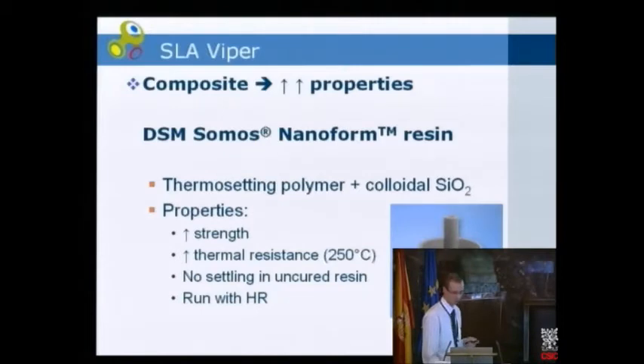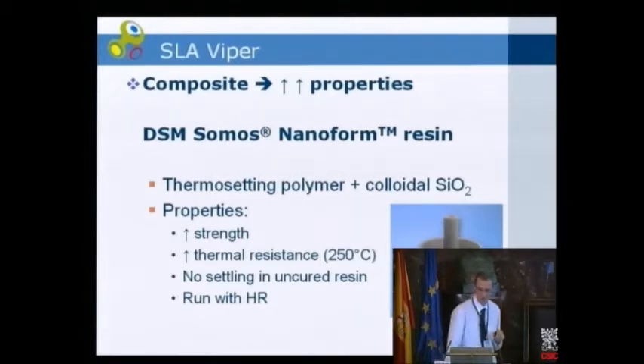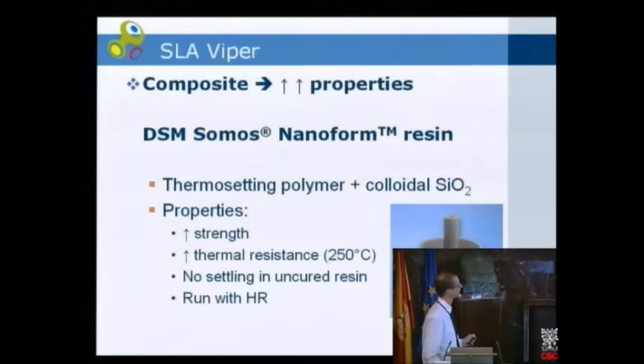Thus, with this technology we can make some composite parts. The interest of making a composite is to improve the properties of the final part. The company DSM Somos produced a new resin called Nanoform. This resin is a thermosetting polymer that is loaded with silicon oxide nanoparticles. These nanoparticles increase the strength of the final part and increase its thermal resistance too, and because of the small size of these particles, there is no settling inside the uncured resin, so it's a stable product. And because of this very small size of the nanoparticles, it can run in high resolution mode, thus we can produce very small details in the part.